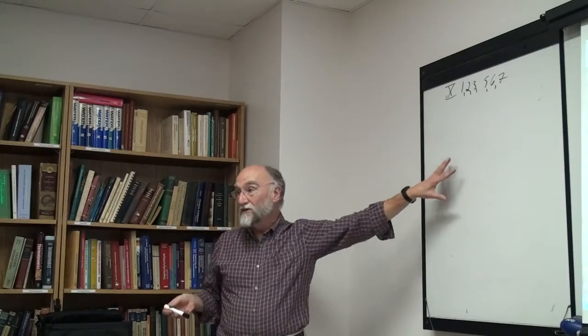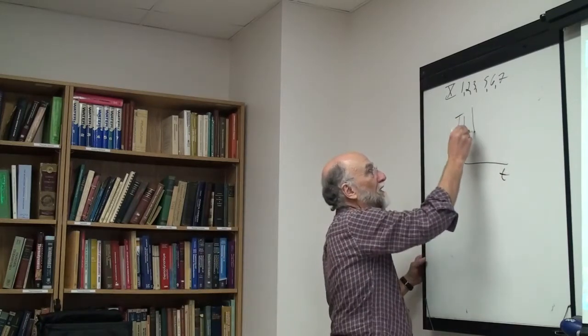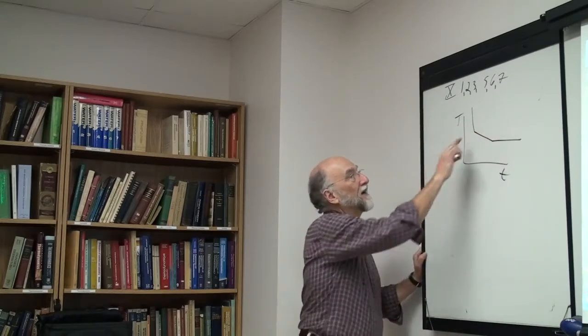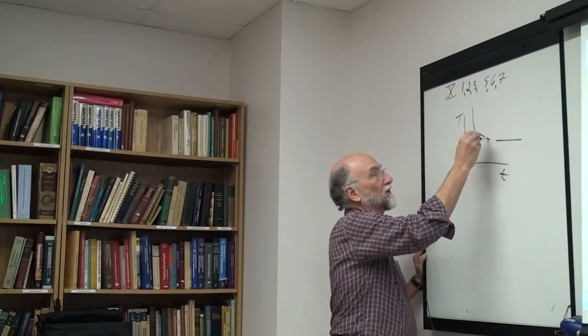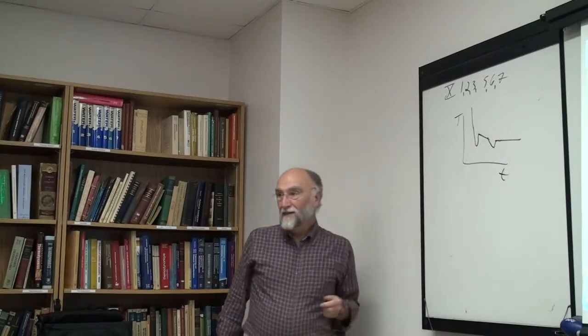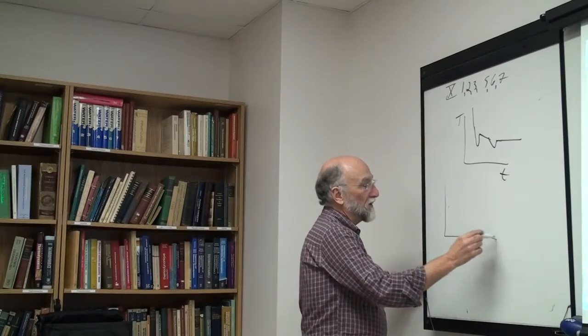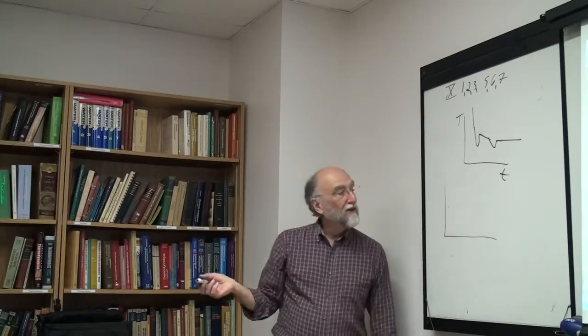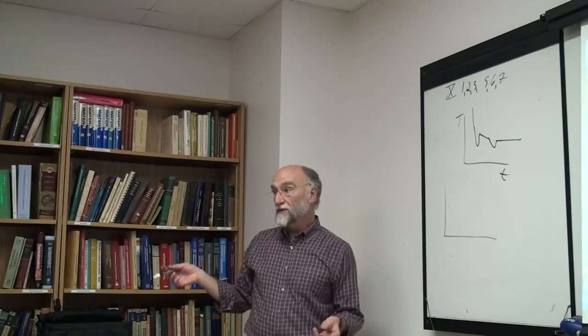You all know differential thermal analysis? This was straight thermal analysis. When you do straight thermal analysis, you do temperature versus time, and you see the thing, and you'll also see your supercooling. Okay, now you do differential thermal analysis. What you're doing is you're measuring the temperature of the furnace outside, and you're measuring the difference in temperature between your sample and the reference. It doesn't change state.